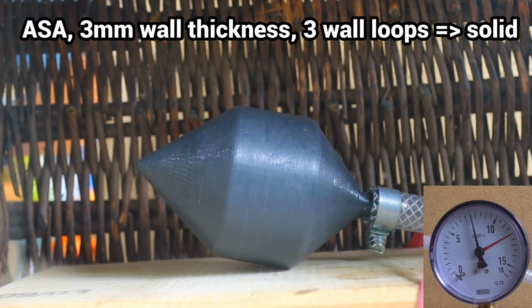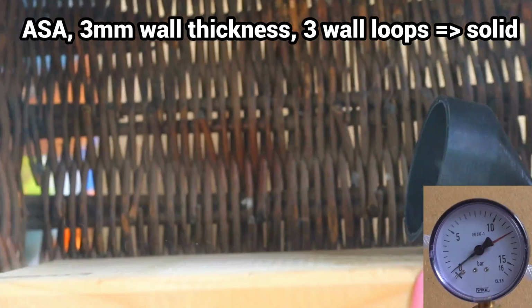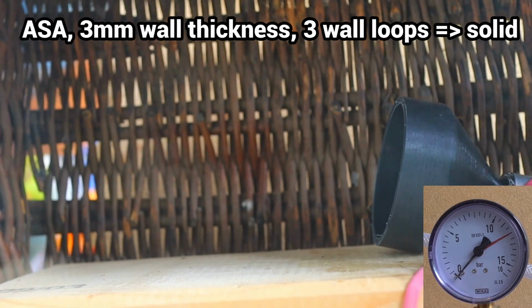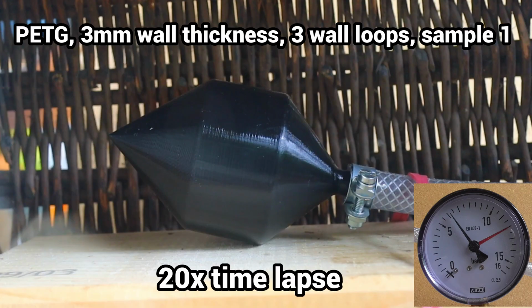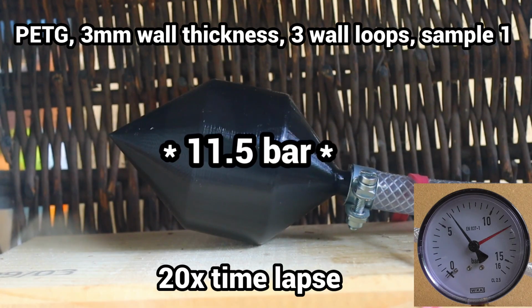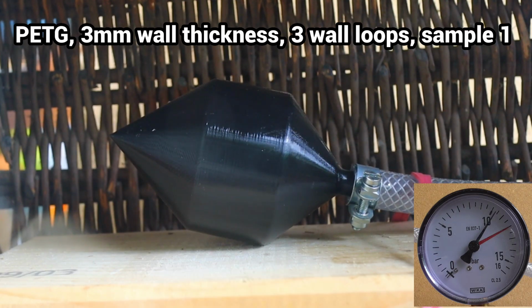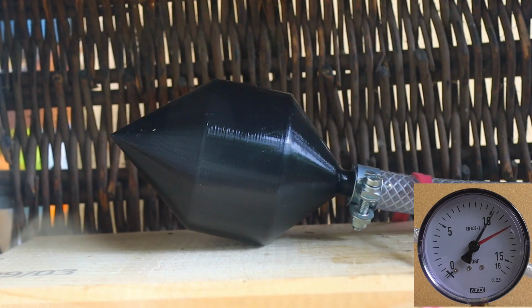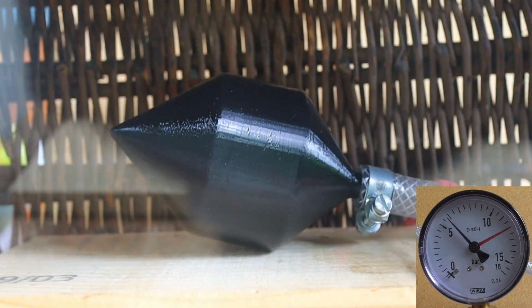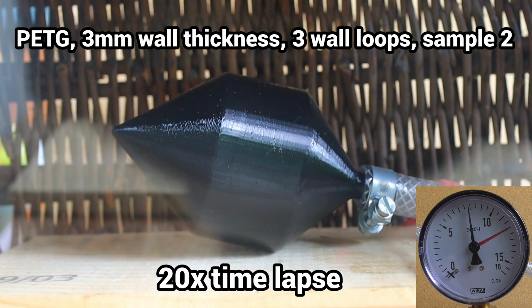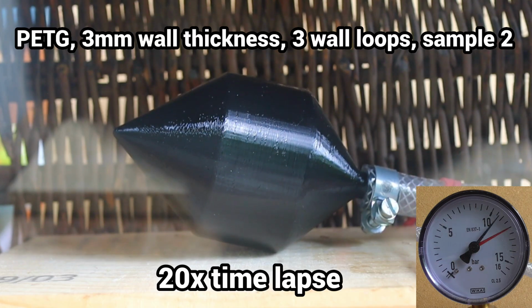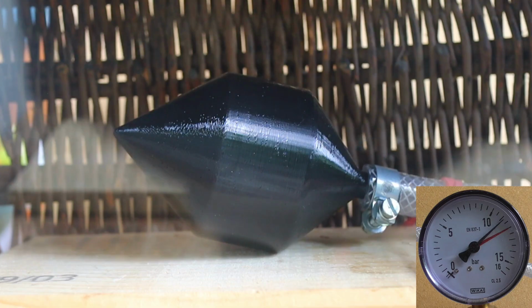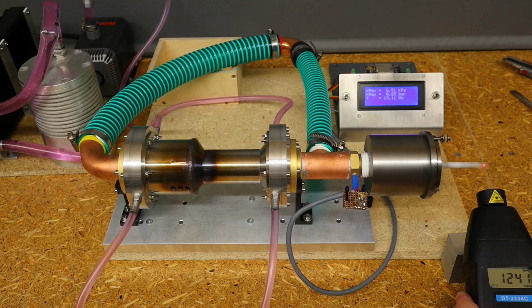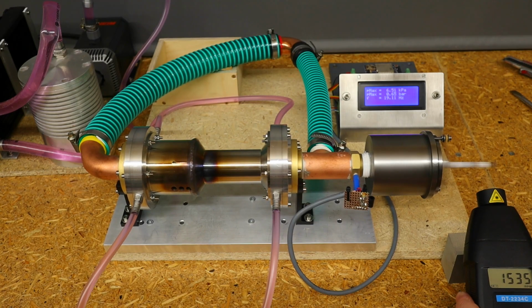With 3 mm wall thickness and 3 wall loops, ASA bursts at 8 bar. PETG with 6 solid walls is stable up to 8.5 bars. Above this, it develops a small, permanent leak. I am very satisfied with these first results. With a solid printed wall thickness of 3 mm, pressures up to 10 bar are possible, making the use of 3D printed parts in the thermoacoustic Stirling engine perfectly reasonable.